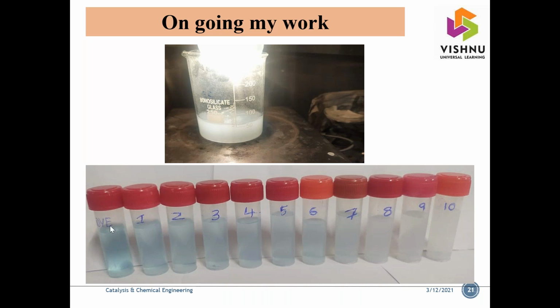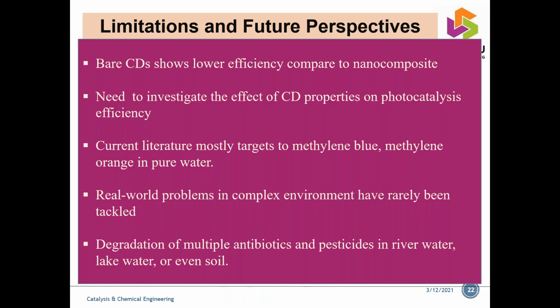Initially it is the dye. Upon increasing the catalyst concentration, we can see complete degradation from 1 to 10. So if we can prepare a better nanocomposite, carbon dots with metals can be the best alternative for water purification. Few carbon-based nanocomposites are already developed, but there are some limitations. Carbon dots alone show very low photocatalytic efficiency compared to the nanocomposites.